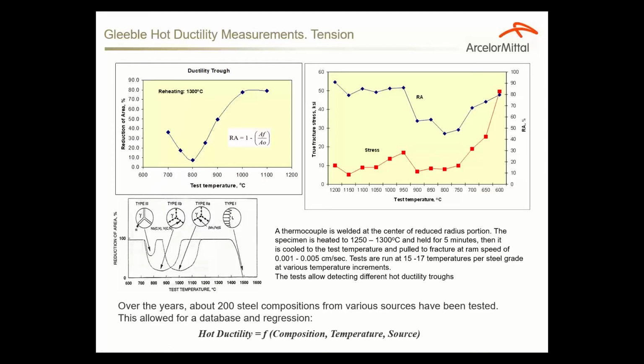What is interesting is, over the years, we tested about 200 compositions from various slab sources, and we have built a database that allows us for this kind of regression. So when the steel making plant asks us for ductility data, we can do both things. We can test the samples directly, and we can derive the ductility from the regression equations that were built based on our multiple tests done before.